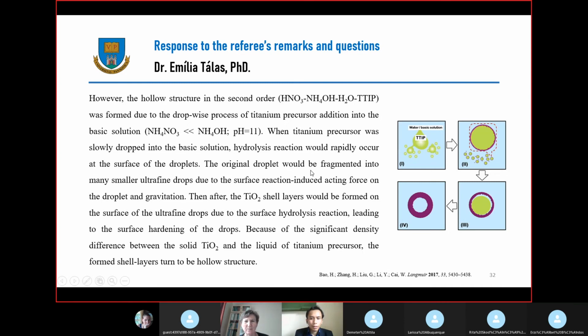So the original droplet fragmented into smaller droplets due to the surface reaction induced acting force on the droplet and the gravitation. Then the titanium shell layer will be formed on the surface of the droplet, and the small droplet, due to the surface hydrolysis reaction, leads to the surface hardening of the drop. Because of the significant density difference between the solid titanium dioxide on the surface and the liquid in the center, the liquid will release and then form the shell hollow structure.